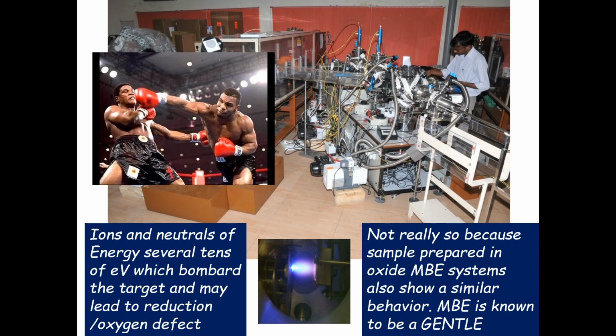So people say that you are doing PLD. There are many non-believers, and they say that the material that you create is highly disordered, damaged, and whatever you are seeing, this 2D electron gas, is because of oxygen vacancies and this and that. They say you use a gentle process, very, very gentle. But I must tell you, this is an old picture now. The story has changed, so I should change my picture.